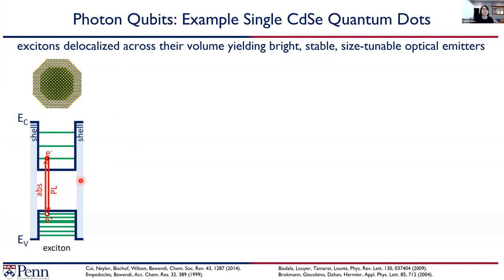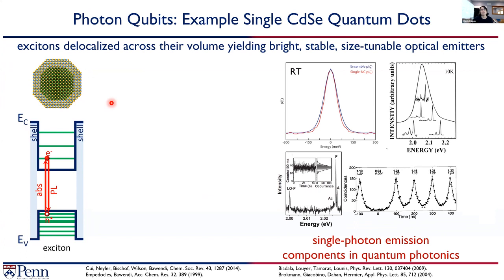And so in fact, some of these compositions are commercialized if you buy a quantum dot television, where the luminescence, in fact, and the yield is extremely high. So we know we can really make very bright and stable optical emitters from colloidal quantum dots. And over time, the ability to control the size distribution of these materials means that you can see spectroscopically that at room temperature, the line width of an ensemble is not that much different in the best quantum dot samples as you get from single particles. This is early luminescence spectra at low temperature, where you can see the vibronic progression characteristic of individual dots and the hundreds of microelectron volt line widths that can be achieved.